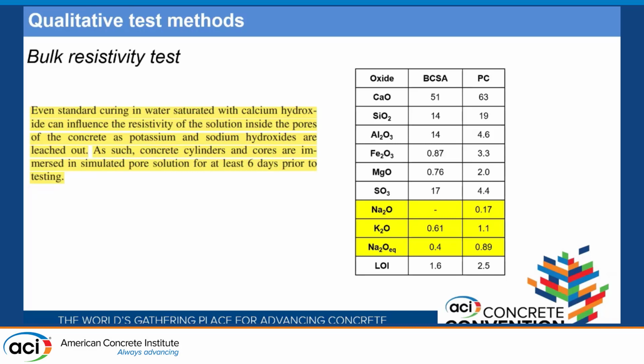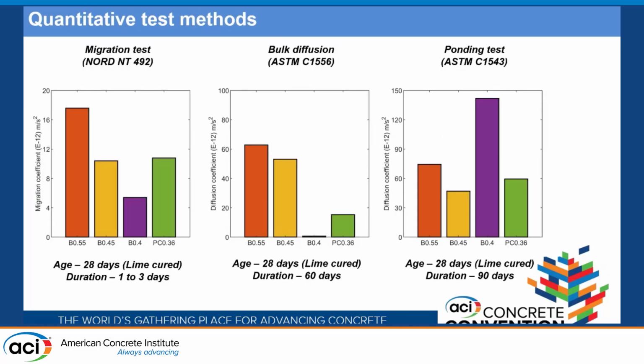So when we look into the oxide composition of BCSA and Portland cement, you can see specifically that the BCSA has low alkalis compared to Portland cement. One possibility is, are we introducing more alkalis into the pore solution in that aspect and making it conductive, which is impacting the overall resistivity of the concrete itself? That's something we need to further study and investigate.